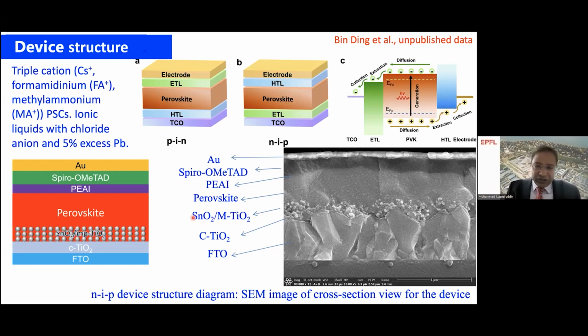Now, if you look at the cross-sectional diagram of our perovskite solar cells, on the left side it's a cartoon. On the right side is a cross-sectional image of one of our cells. We have a conducting glass, on which we deposit a very thin compact layer of TiO2, followed by an ETL layer, that's the electron transport layer, composed of mixed oxide, titanium dioxide and tin oxide. Then we deposit a perovskite layer 500 to 600 nanometers thick. Then you have a very thin layer of two-dimensional perovskite, that's phenylethylamine iodide, and you will see in coming slides what two-dimensional perovskite is. Followed by a hole transport material and gold as a contact.